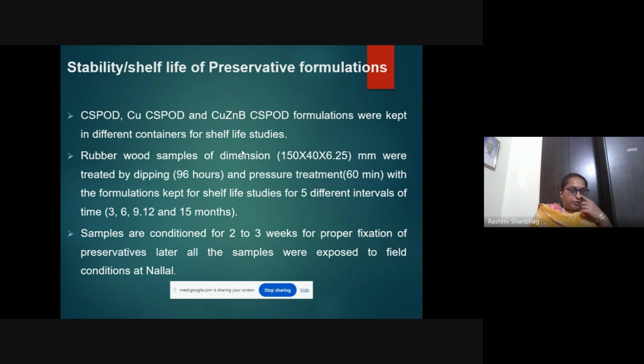So what we did was we kept these samples for different durations, like 3 months. After preparation of the formulation, we kept them initially for 3 months, 6 months, 9 months, 12 months, and 15 months. For these samples, we again treated. After the 3 months, we took the sample, we treated the wood with the sample.